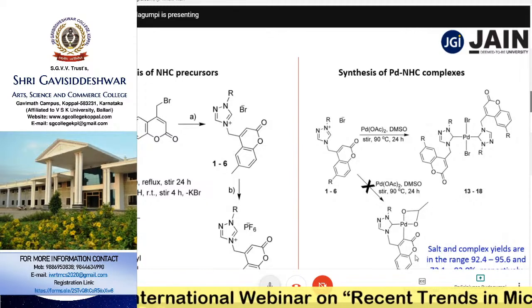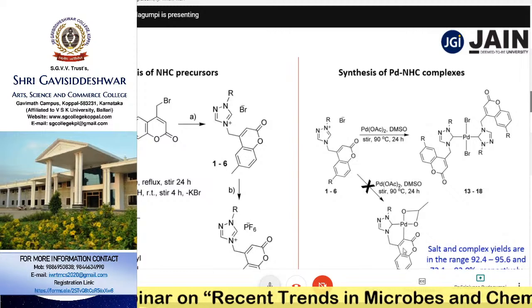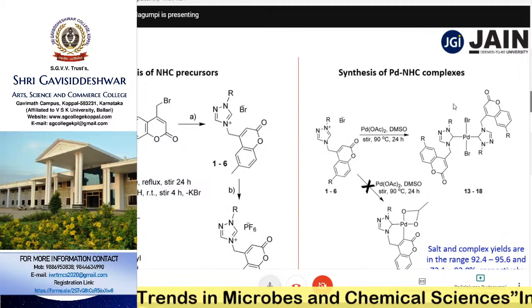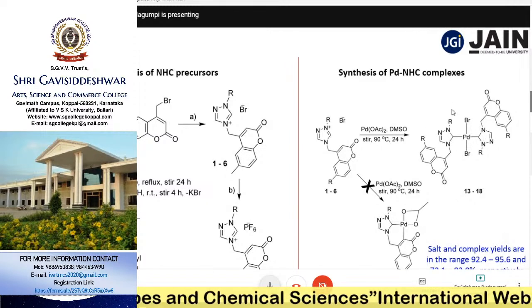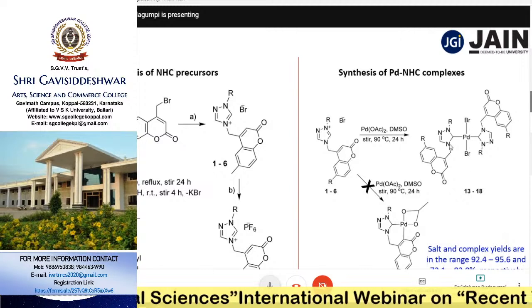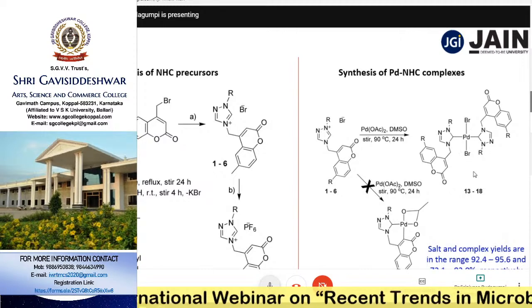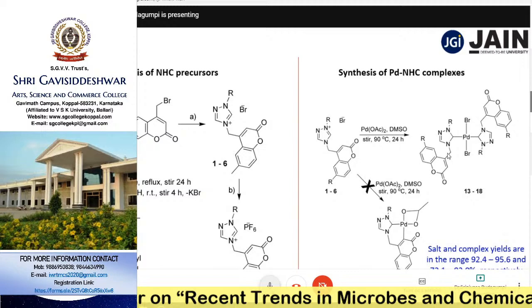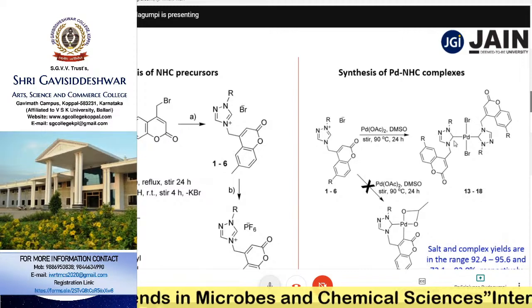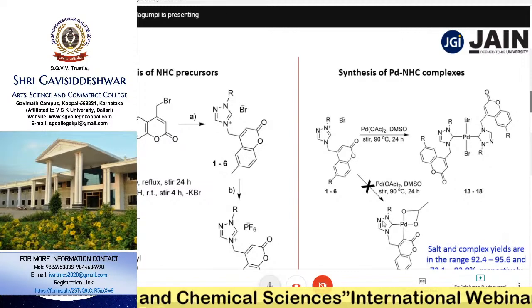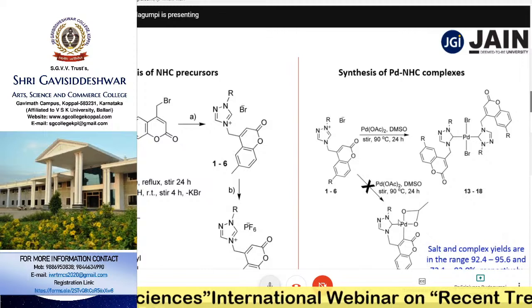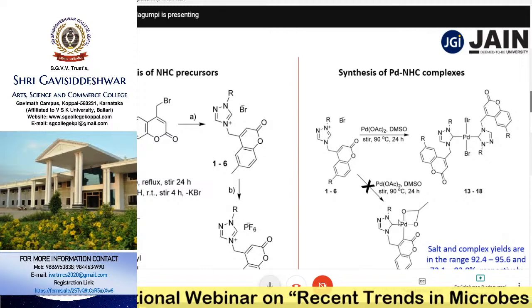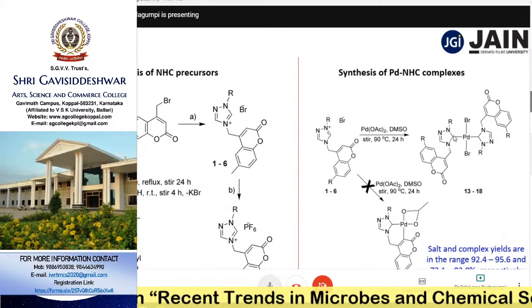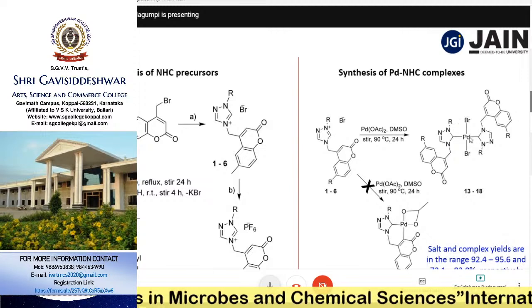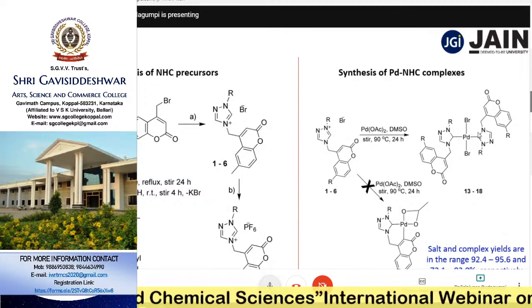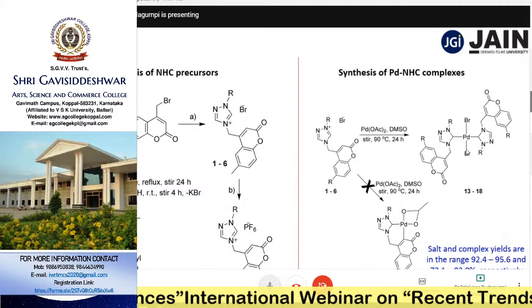Unfortunately, this was not the structure of the molecule we got. Instead, we got bis NHC coordinated palladium complexes in trans position, right? So this is the complex eventually formed. That's because of the steric bulk. This is not formed because of kinetic or thermodynamic restrictions. We ended up with the bis NHC coordinated palladium complexes, which are square planar in nature and trans geometry,